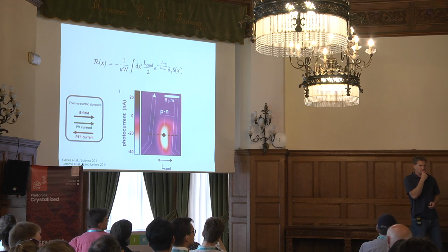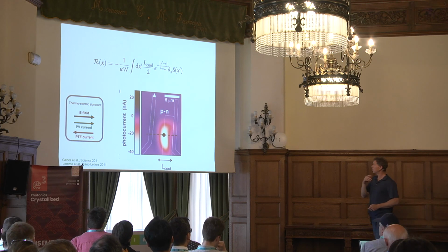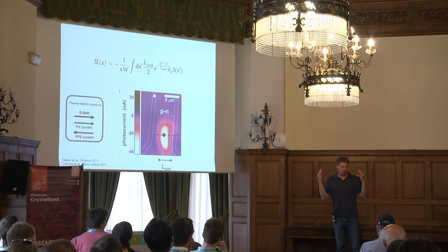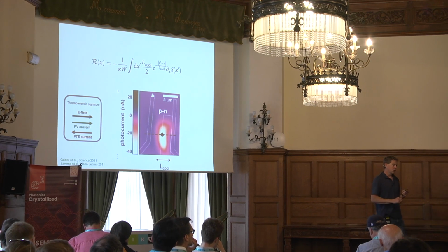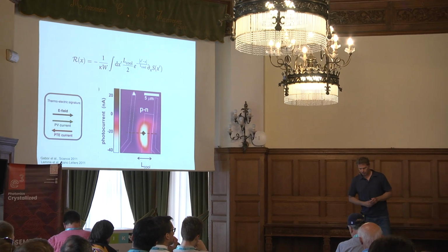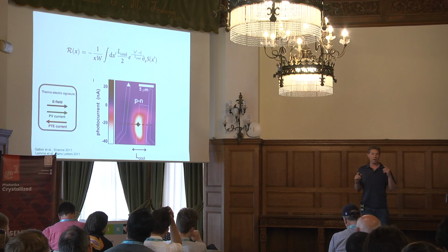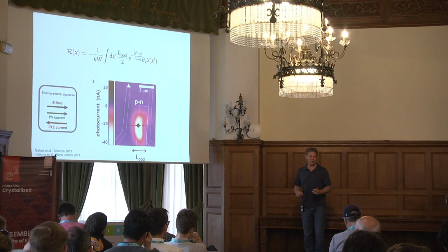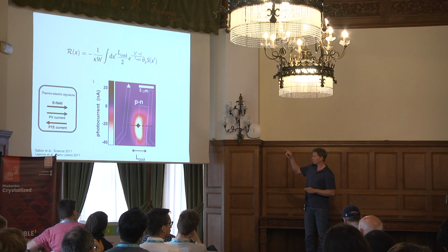Frank, how about the substrate? Do you take into account any substrate effects? Yes, actually, the cooling length is in many cases dominated by the substrate. The heat is lost into substrate phonons, for example. There's also coupling to graphene phonons, but this is very weak. And we have a paper, which is not in the slides, that shows the cooling to the hyperbolic phonons in boron nitride is very strong. So the hyperbolic character that Pablo was talking about is actually important for the electron cooling.